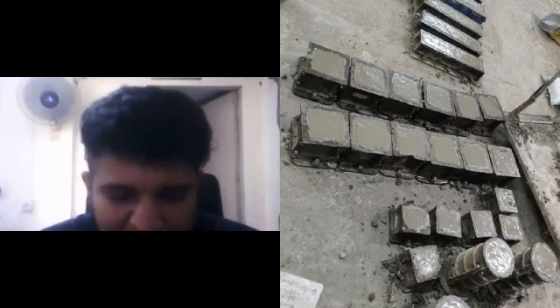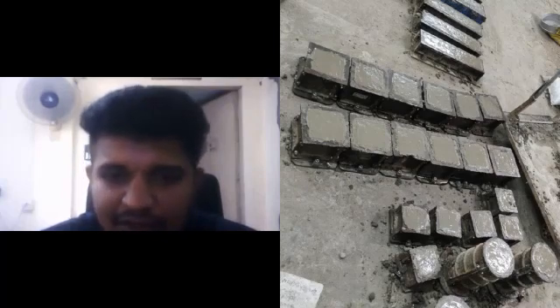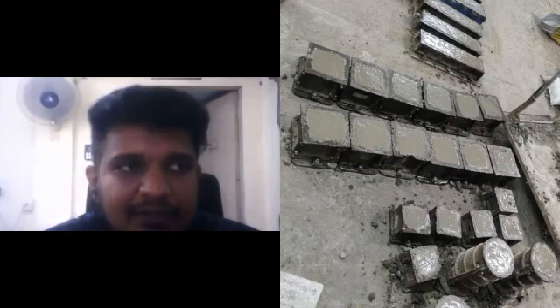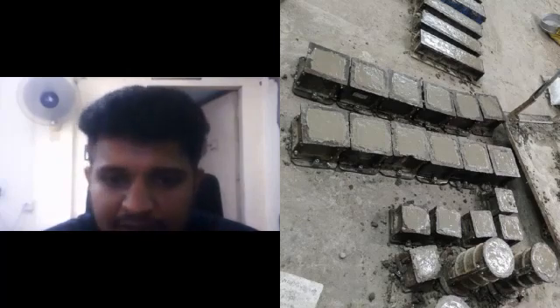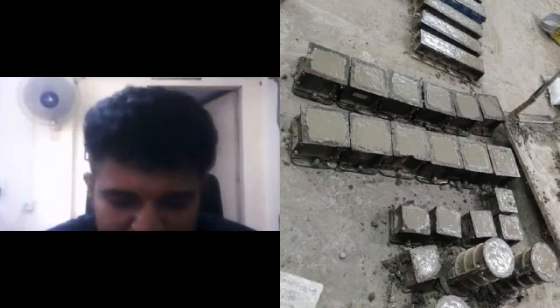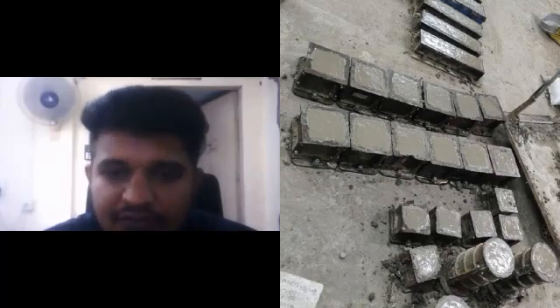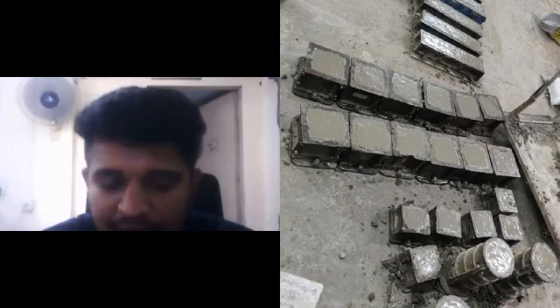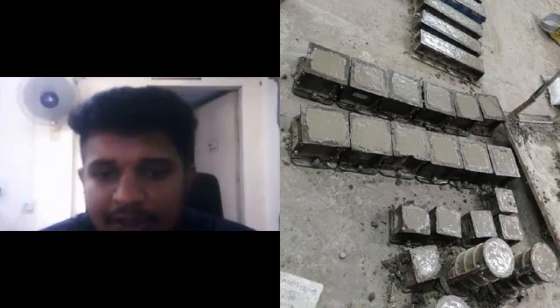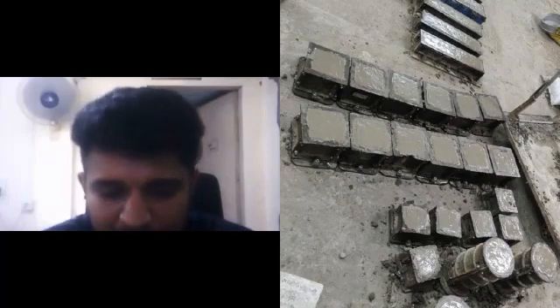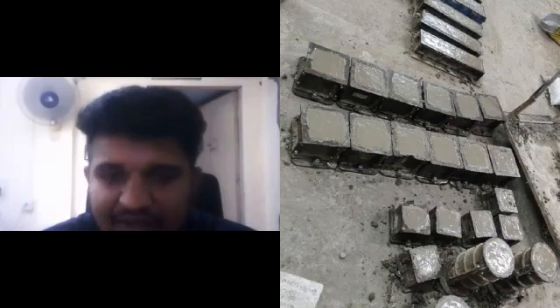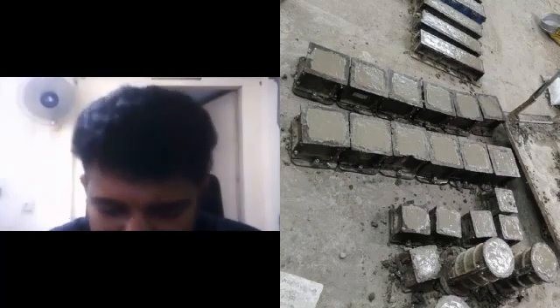So multiple field trials were also carried out after successful laboratory experimentation. I evaluated my developed concrete containing the new generation admixture for almost 1.5 years to ascertain the long-term behavior, not just the physical and mechanical properties, but also the durability properties of the concrete. And when all of them revealed satisfactory results, I carried out 2 field experimentations.